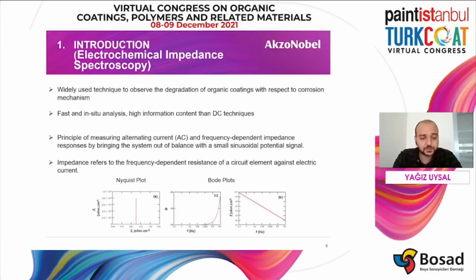Electrochemical impedance measurements provide information about the impedance of the painted metal system before corrosion starts, and by comparing the different systems, inference can be made about which one has more protective properties. Also, impedance values measured after any system has been corroded can provide more information about the corrosion mechanism that will occur while using the coating under field conditions.